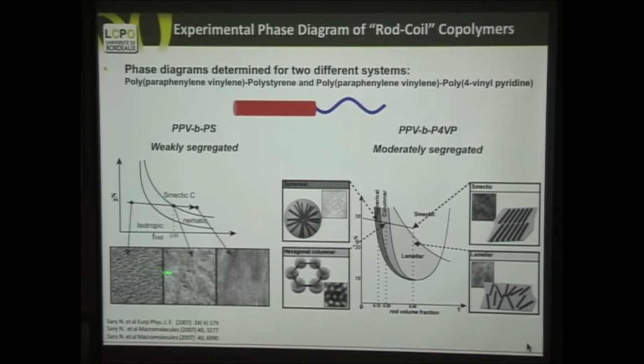And here we make various polymers to establish the phase diagrams. When the interactions are weak here, then we have this phase diagram where we have isotropic mixture, we have a smectic transition here, and then we go to the nematic. In this one, when we have more interactions between the two polymers, then we can have all the types of features, the spheres, the cylinders, the lamellae, but they have two different lamellae here, since we can play with the interaction of the rods, and this is a theoretical line that predicts that. You can have the rods align well in the sublayer or be disaligned. But that will be important for the transport of the charges, the electrical charges.